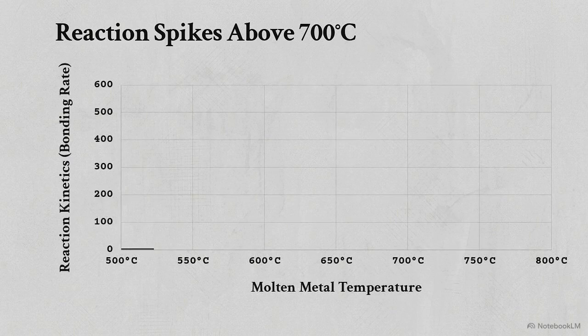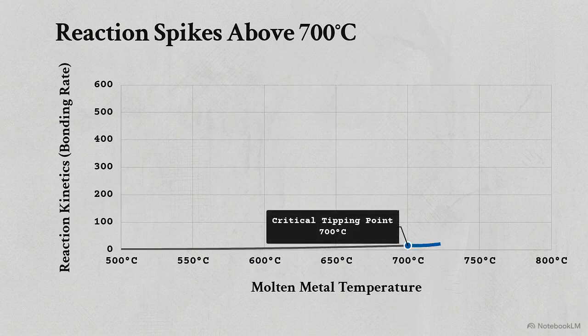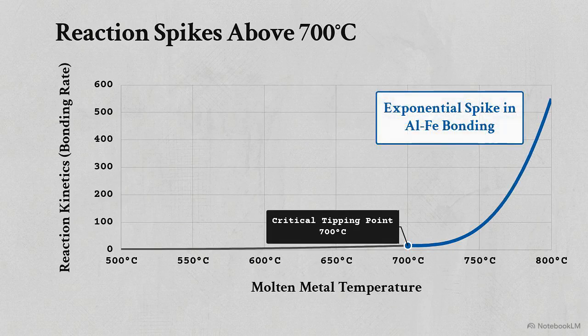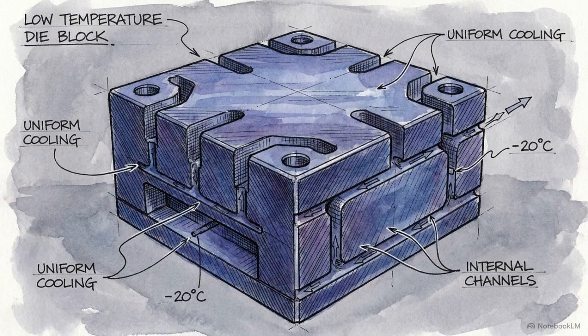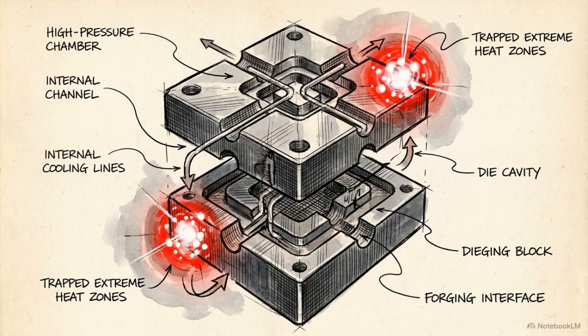This graph charts the reaction rate of aluminum and iron across different temperatures. The curve remains relatively flat until the molten metal temperature crosses 700 degrees Celsius, at which point the reaction kinetics shift rapidly and the intermetallic bonding spikes exponentially. Uneven thermodynamics within the die block compound this problem. Areas that fail to cool properly become localized hotspots, serving as direct ignition points for soldering.